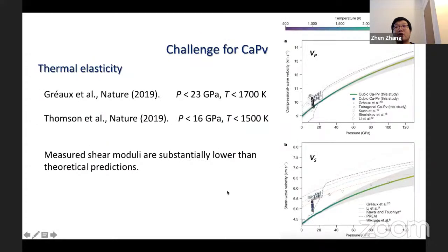Thermoelasticity of calcium perovskite was measured recently by the following two works. The bulk and shear moduli can be derived from the measured longitudinal and shear sound velocities. However, the experiments were conducted below the lower mantle pressure-temperature range, and the results were extrapolated to the entire lower mantle. Also, the measured shear moduli are substantially lower than the predictions by computations.